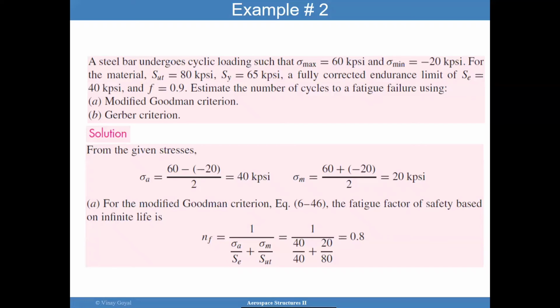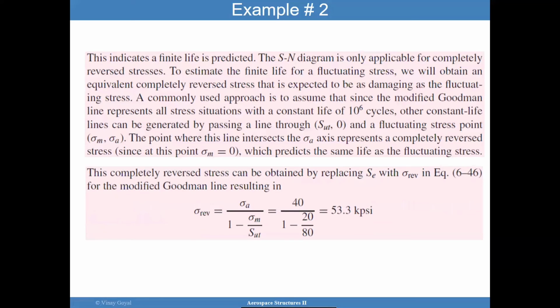So we want to use this criterion. And now for the modified Goodman criteria, the fatigue factor of safety based on infinite life is using this formula here. So we put it in here. So 1 divided by sigma alternating is 40. The endurance is given to you as 40. The mean stress is found as 20. And then the ultimate tensile strength is 80. So you plug it all in and you get 0.8. That's a factor of safety less than 1. So clearly, we are predicting a finite life now.